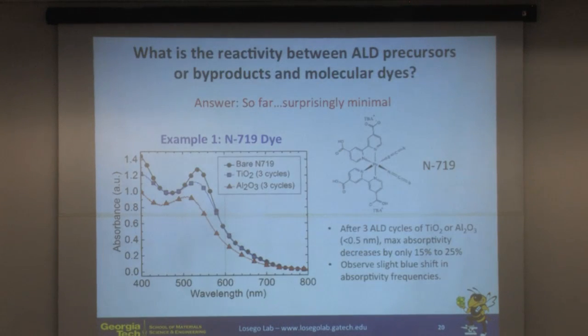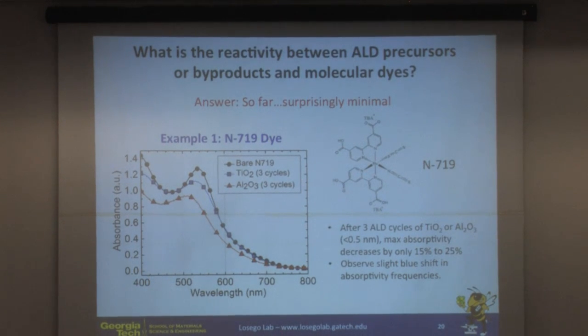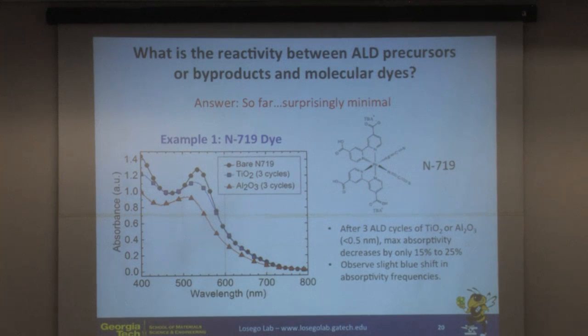And the reason that people didn't do that was because they assumed that these very reactive ALD precursors react with their molecular functionality. And we kind of thought that that might happen as well. It turns out that so far we haven't really seen much degradation, or much less degradation than we would have expected when we do these processes. And so thermally, we're usually not very limited.